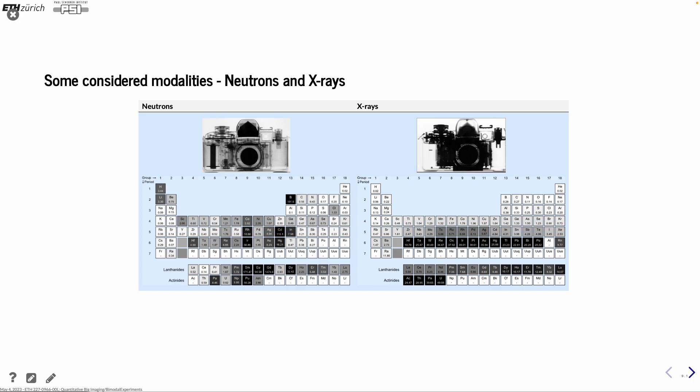One very good example is hydrogen. The lightest element has a quite high attenuation with neutrons, but you don't see it at all using X-rays. So that is the motivation to use the two. In many experiments, also lithium for batteries is also a good component, which we also trace. And we actually do bimodal experiments on batteries and on fuel cells, porous media examples, and so on. In other cases, maybe you just can't come through the material like many of the materials here, like lead, gold, et cetera. You have longer penetration depth with the neutrons. But there are other sides where neutrons are not so good. So you have to select it in a way that you can use it correctly.